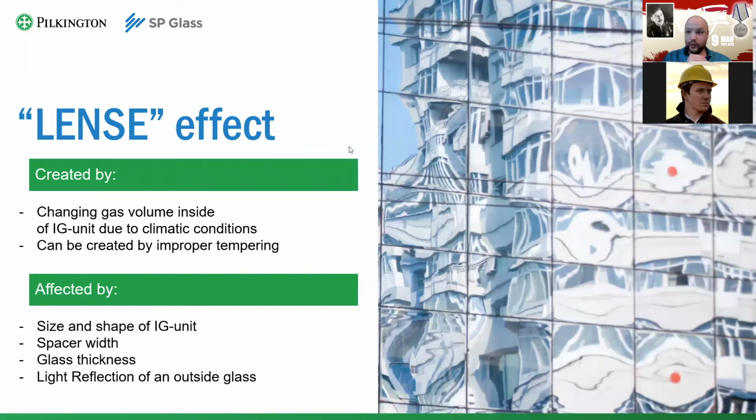That is because there is a lot more than just distortions you have to take into account. First, for hot climates, it's much easier to choose a proper spacer depending on the size of an IG unit, because you don't have negative temperatures. So the IG unit doesn't bend inwards with the glass touching each other. So for a Russian climate, I would say go for a wider spacer. In your climate, I would say you have to balance your option, taking into account the size of your IG unit.